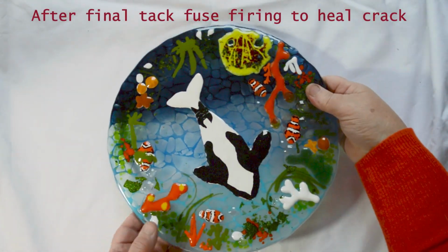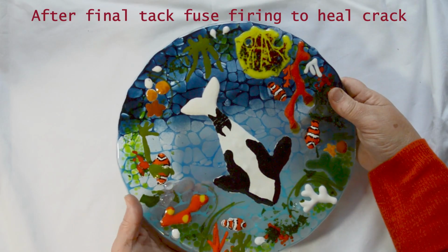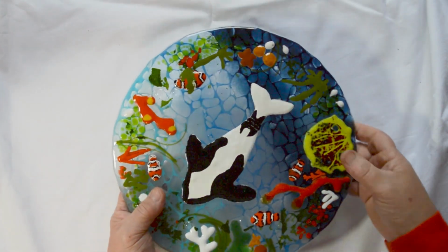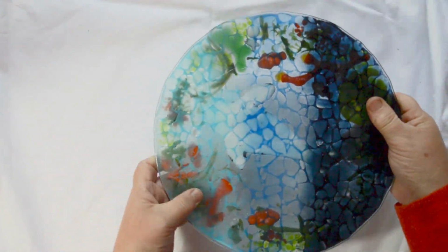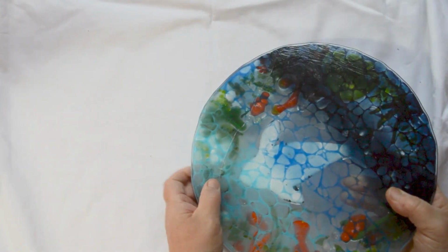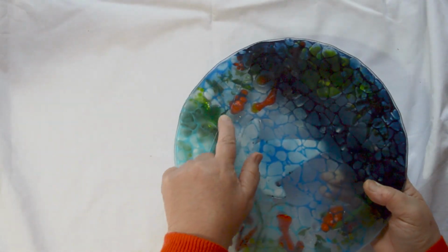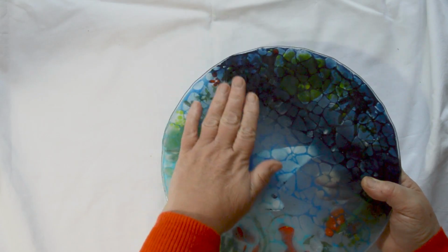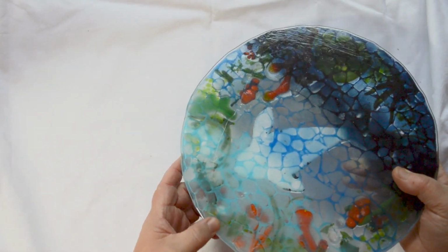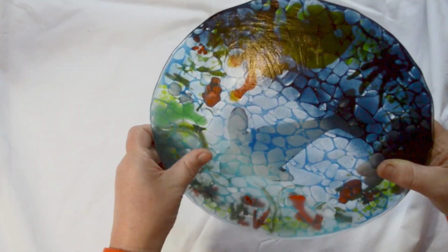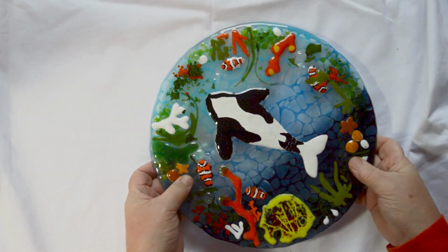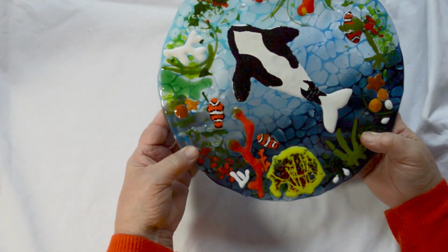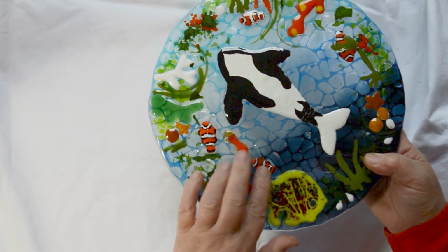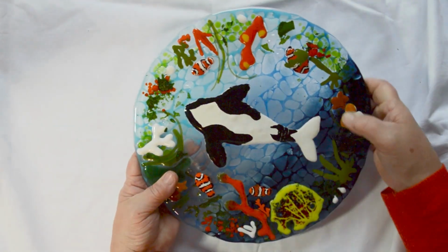So here we are after the tack fuse schedule suggested for an 18mm thickness slab. To be honest, I'm a little bit disappointed as some of the definition has been lost. It looks like it's gone through a contour fuse rather than a tack fuse, but the crack has healed, which is one good thing. The clownfish especially have flattened out and don't look as realistic. It could be tidied up with some enamel work, but I don't want to risk firing it again.